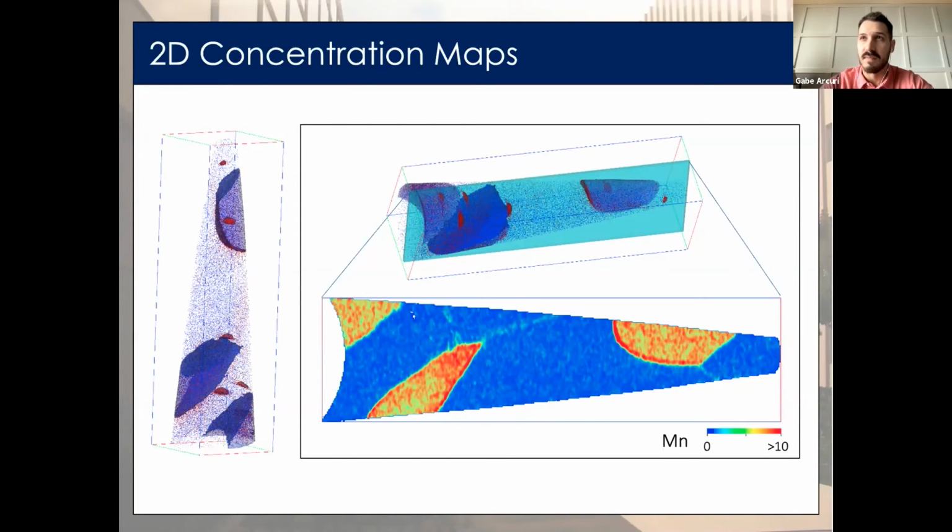And this will help us emphasize particular features. So for example, if thickness is too small, it may fail to incorporate smaller features, and it might limit the number of atoms available in the analysis. And that can affect the quality of our stats. However, if the region of interest is too thick, then features occurring at depth in the Z direction in the volume may overlap in our XY plane, and thus that will be reflected in our 2D map.